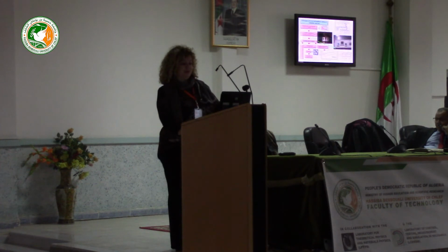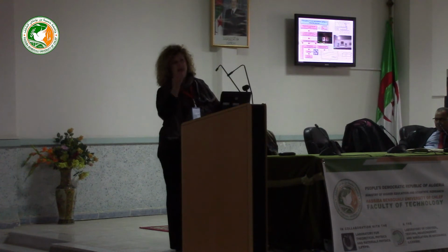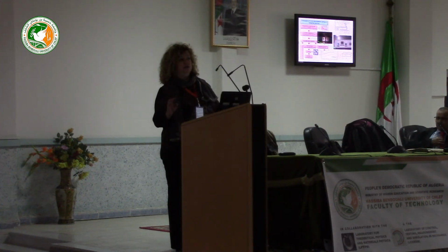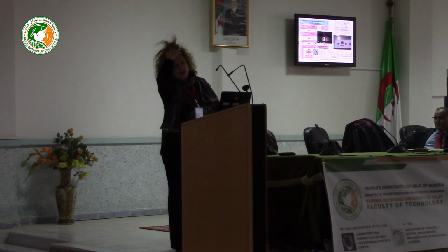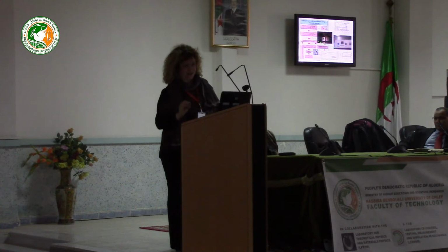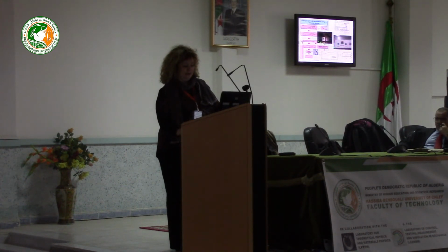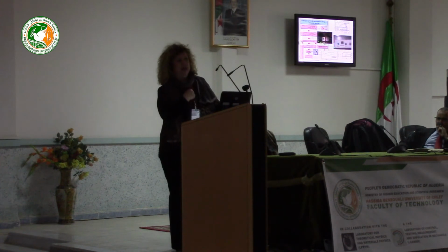So we put our specimen in the device which we call the thermomechanical simulator, and we do the simulation, which will last depending on delta t 8/5. It means the delta t 8/5 is the time of the transformation between 800 and 500 degrees. So our experiment with one specimen will last, let's say, around 30 to 50 seconds.